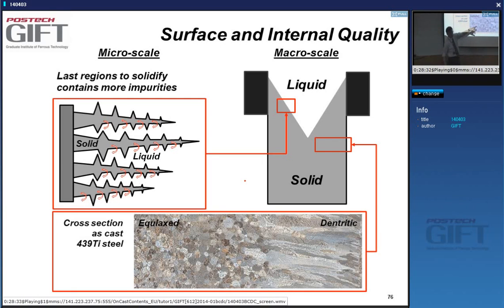This is actually a continuously cast microstructure. It's an example of a 439 stainless steel. It doesn't go through transformations like regular carbon steels or austenitic stainless steel, so the microstructure you get in the slab is actually the high temperature structure. You can see that close to the wall of the copper mold, you get very quick solidification, and so you get small grains. That's good, but inside, the cooling rates drop dramatically, and you get these dendritic microstructures.